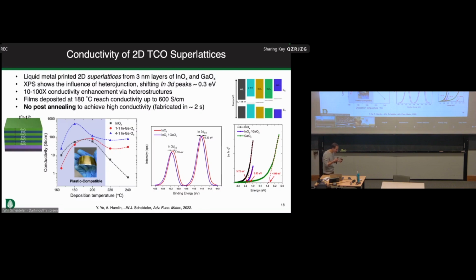Okay, well, as a materials scientist, as an experimentalist, how do you understand these properties? Well, you can do measurements like X-ray photoelectron spectroscopy, and XPS can tell you from the perspective of the photoelectrons emitted that there's a shift in the Fermi level. So that's the first sign that corresponds to our hypothesis of the modulation doping. The second thing we might be able to observe is that there's actually a change in the visible range absorption. It's kind of a funny principle, actually, that if you take this gallium oxide, which is more transparent, and stack it on top of the indium oxide, the combination becomes more transparent. So you've lowered absorption by shifting the Fermi level in the indium oxide.